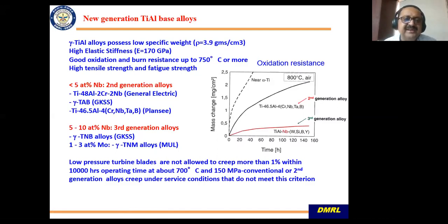Now there are different generations of gamma aluminides. There is the first generation, which has niobium percentage much lower, in the order of 1 or 2%, and then you have the second generation alloy, which has niobium in the range of less than 5 atom percent, and the third generation alloy, which has slightly higher niobium percentages, and then there are complex other alloying elements which are there.